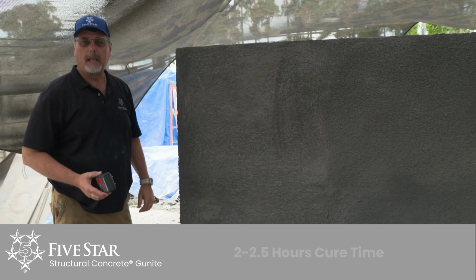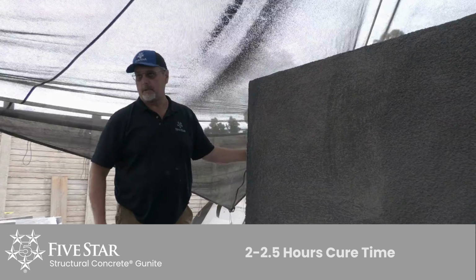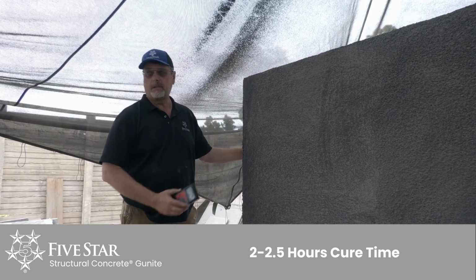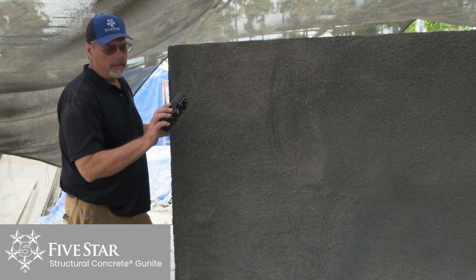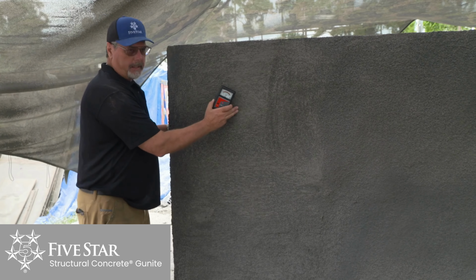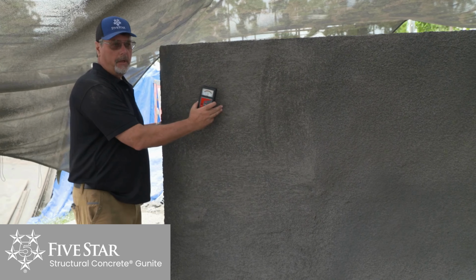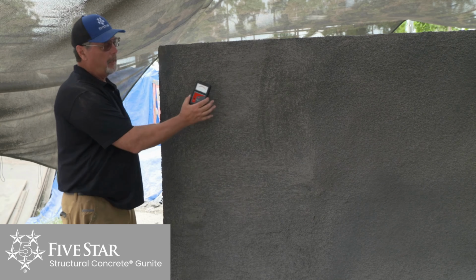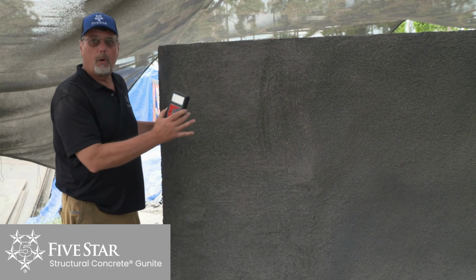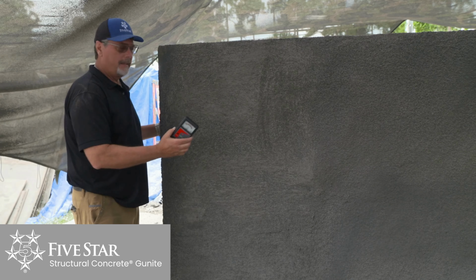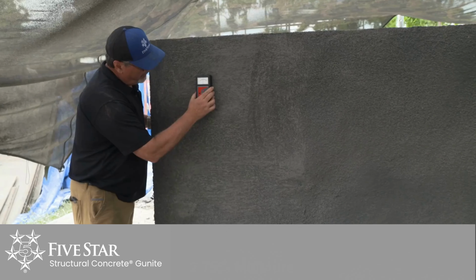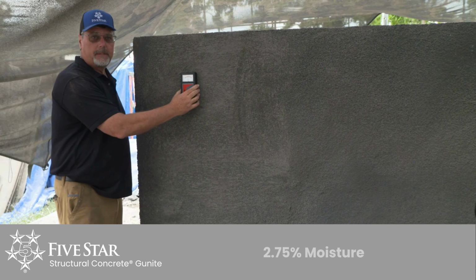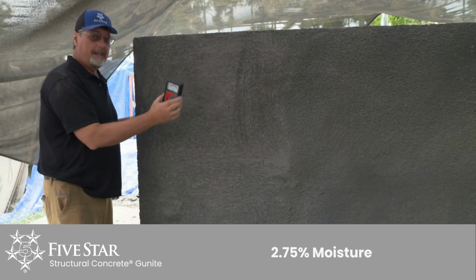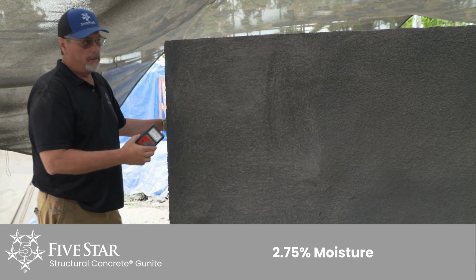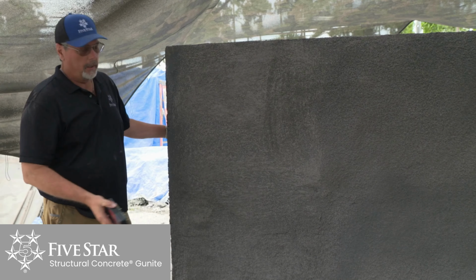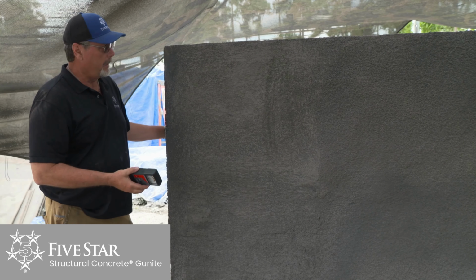Been about 2 to 2.5 hours since we applied this structural gunite material on this wall. We typically use a moisture meter to measure the moisture content, because if the moisture content is above 5%, it will actually bubble and blow off the coating. So we want something less than that. And if I do this right now, we're at about 2.75% moisture in here, which is ideal to apply a coating. So 3 hours, we're going to apply a coating, and you'll see that in a few minutes.